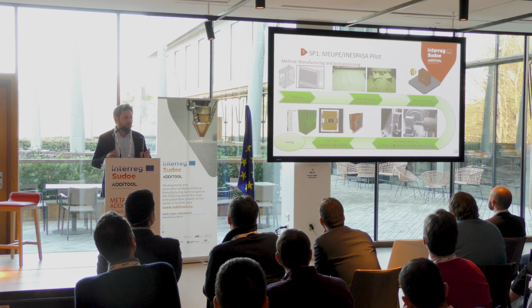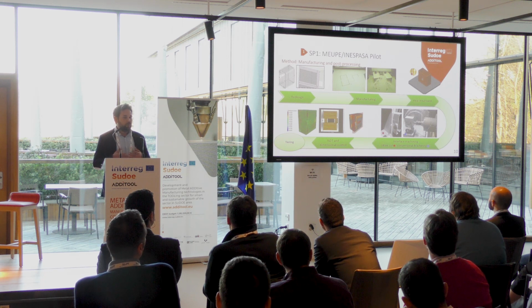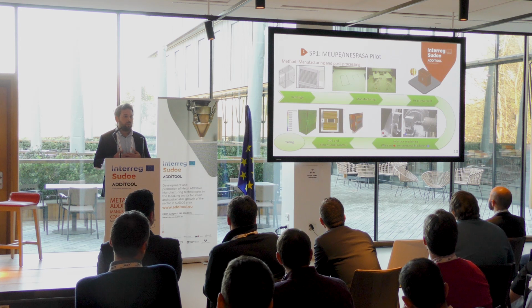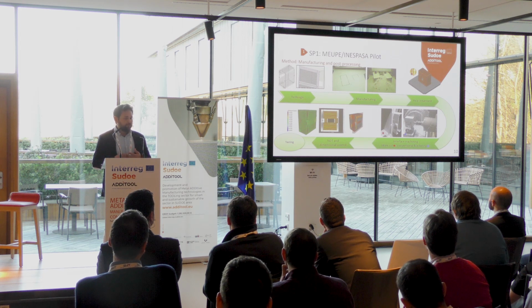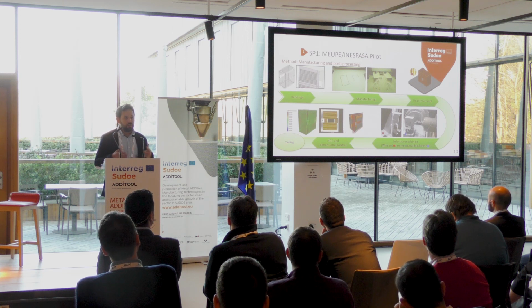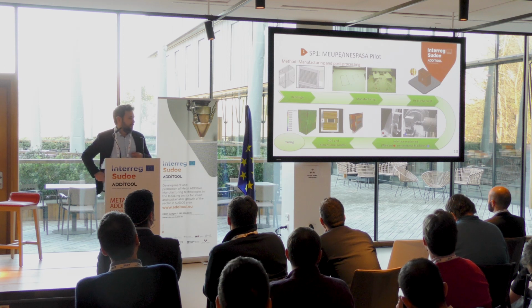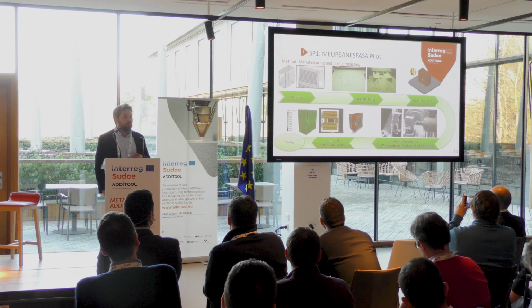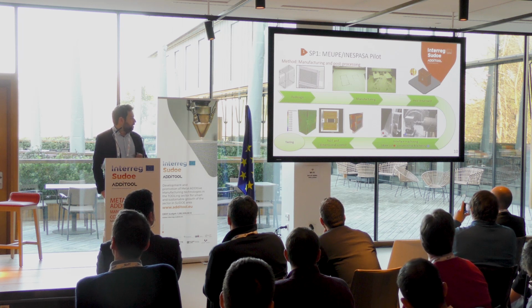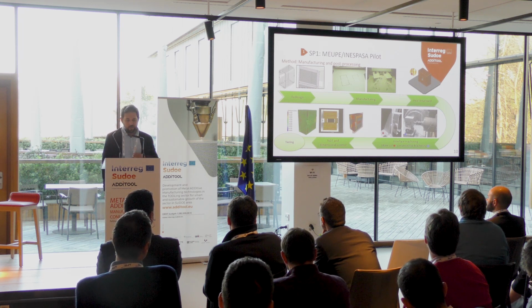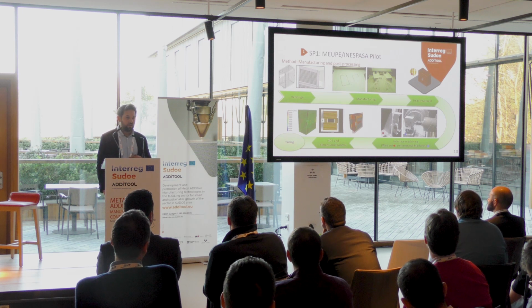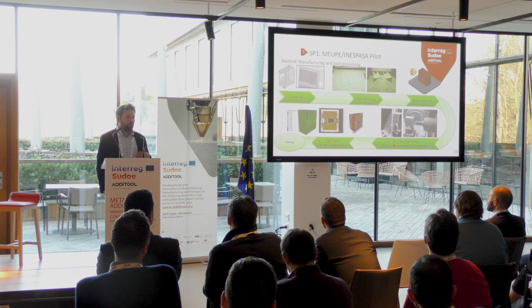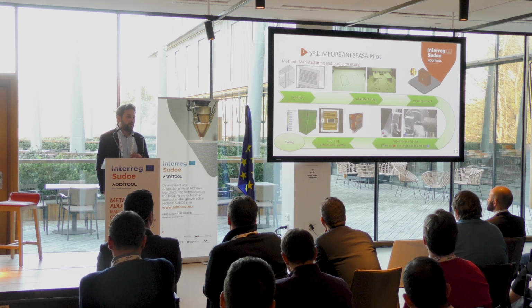One is a demonstrator, just to show the internal cavities, and 2 of them are functional. One of them goes to interface machining with MEUPE to obtain the dimensional requirements that are higher in the interfaces, but we also implemented a wire cut process as we have to extract the component from the building plate, using the same process to make the interfaces on the other side.